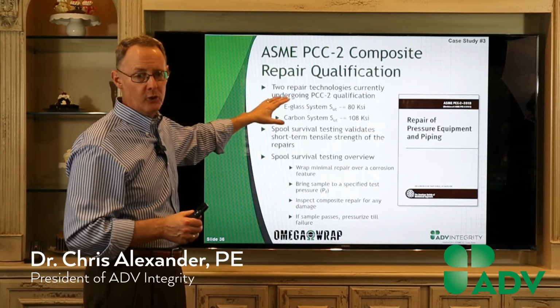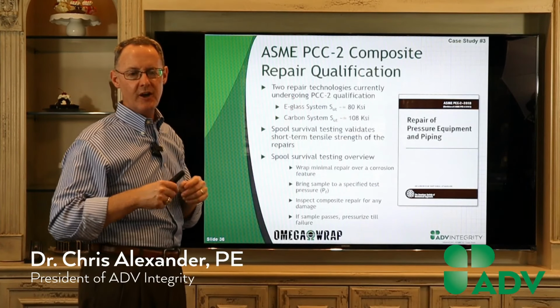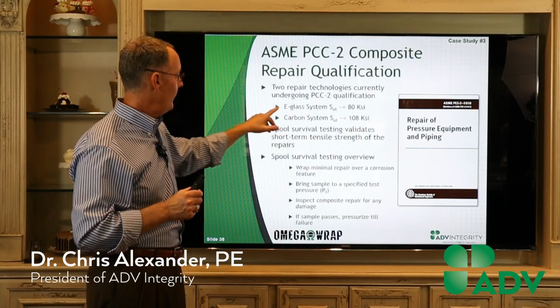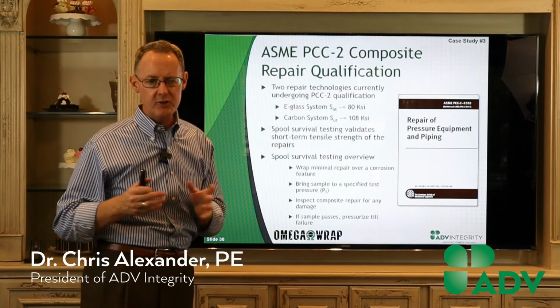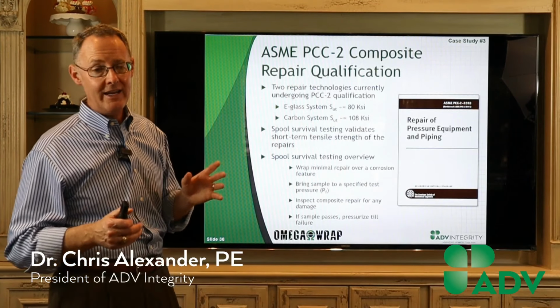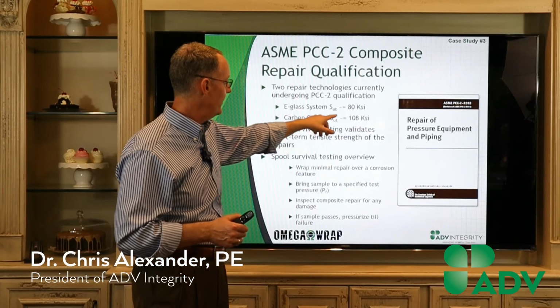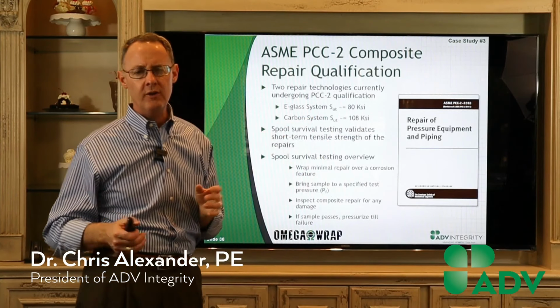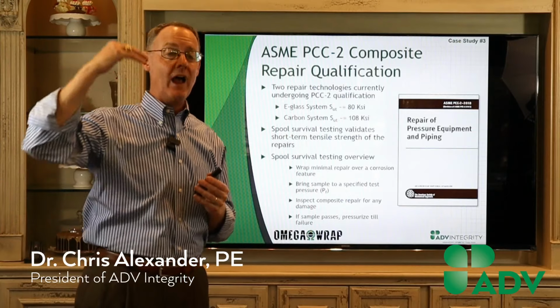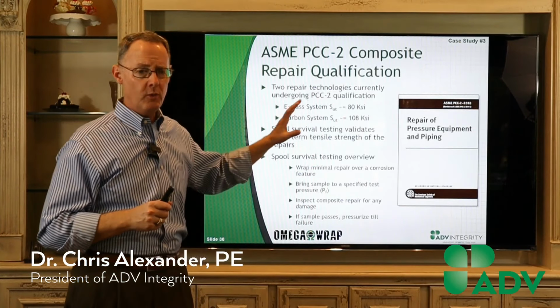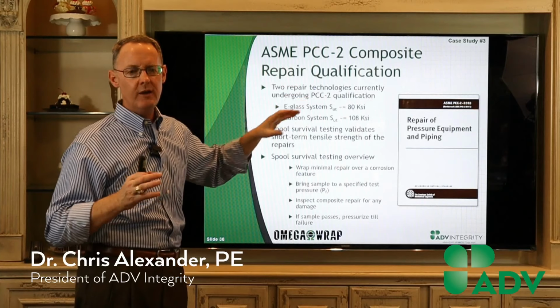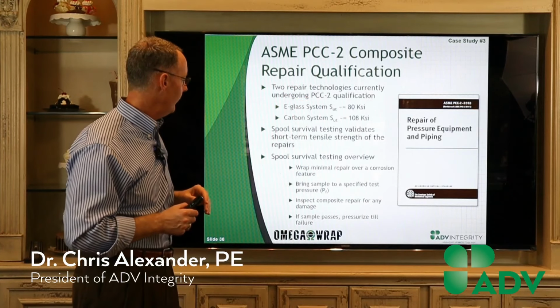And so as I alluded to earlier, we've done a bunch of tensile tests in our little Tinius Olsen machine. And we got an E-glass that's got an ultimate tensile strength of about 80,000 psi, or 80 ksi. The carbon's around 110. We've had some numbers that are way higher than that, but we felt like these were numbers that were pretty representative of the mean with some confidence levels.